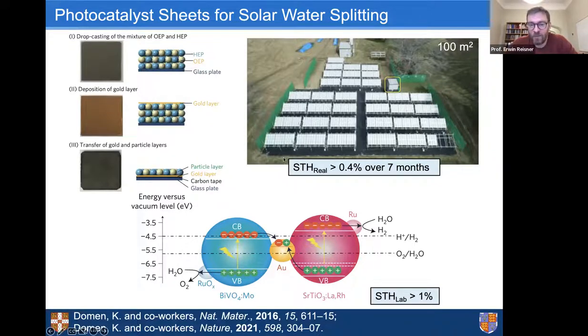And particularly impressive has been that not quite this system, but a single particle lanthanum and rhodium-doped strontium titanate system has been translated to a 100 square meter array of water splitting. And so I think it's a very important demonstration to the world that these things can actually be scaled with efficiencies that are meaningful, of course not commercially viable, but very meaningful, and for quite a long time. 7 months, I think, is amazing. And also the Z-scheme here has already demonstrated efficiencies of more than 1%. So we find this very appealing.